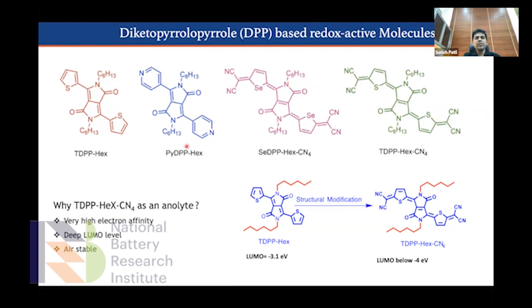Why do we believe in this one? This is exciting because we have a handle in the same molecule. We can cover a very wide range of redox potential window by playing with the functionality. So we synthesized the material. In one of the materials we synthesized in our lab, going from thiophene to nitrile thiophene, we achieved a LUMO, the lowest unoccupied molecular orbital, below -4 eV. By doing that, what did we achieve? Our challenge was a very high electron affinity. It can be easily reduced. It has a deep LUMO level, and when you expose it to air, it is actually a very stable analyte. So that's a challenge in the field.